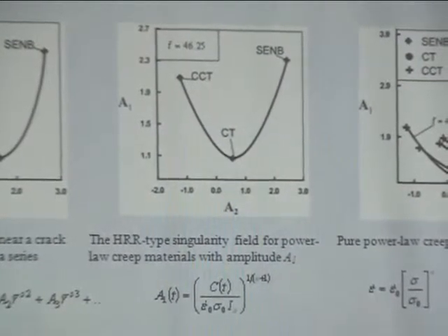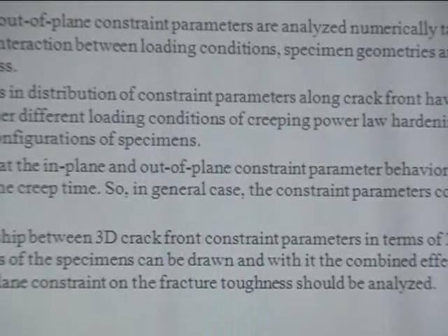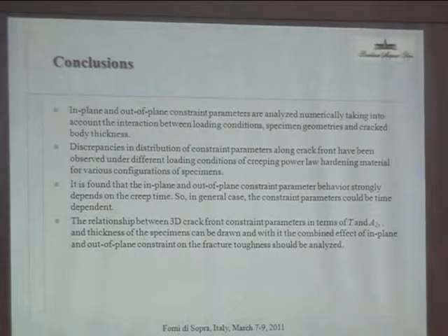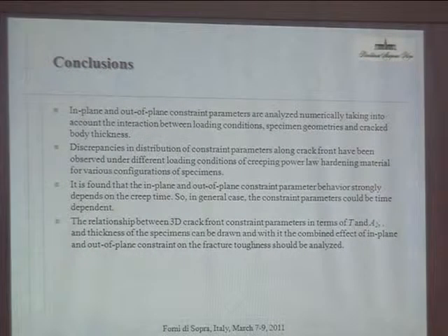And finally, I would like to show you the variation of amplitude factor in the center of the specimens. If we give stress components near the crack tip by the following equations, then A1, A2 and A3 correspond to amplitude factors for the corresponding terms in the expansion of the stress field. It can be seen that there is some shift of these curves constructed for different specimen configurations in the region of low constraint.